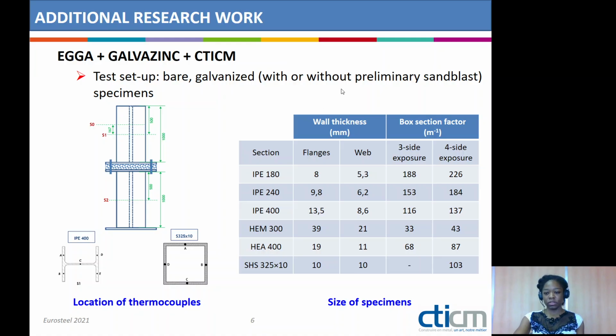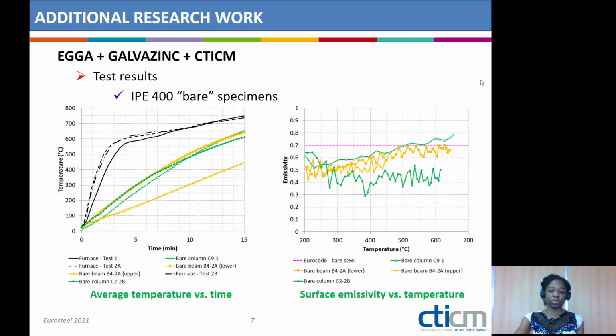You can see that the value of this box section factor ranges from 30 in case of 3-side fire exposure to 230 in case of 4-side fire exposure. So the thermocouples were set on different places on the specimens. And if we have a look at the temperature curves of some specific specimens, such as IPE 400 bare steel columns and beams, you can see that considering a 15 minutes fire exposure to the standard fire curve, you reach a temperature higher than 600 Celsius degrees on the lower flanges of the specimens and on their webs.